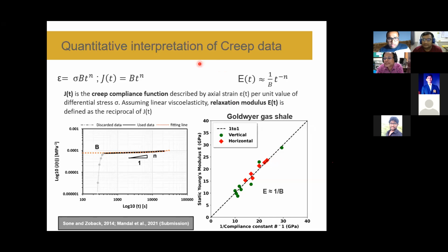How much time does a sample take for a triaxial test? Once you have loaded the sample, you are just controlling the loading and unloading scenario. In this case, we do loading for 5 stages and unloading for 4 stages in total. But if you want a single stage, you just apply the stress, measure your PIP, and then allow the sample to fail. It depends on the logistical challenges of the sample. If you have enough samples, you don't need to do multi-stage tests. You can do it with a single stage also.